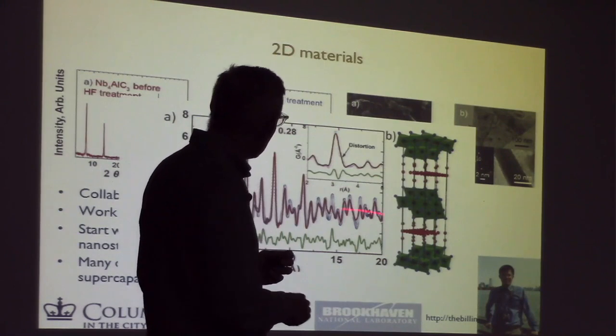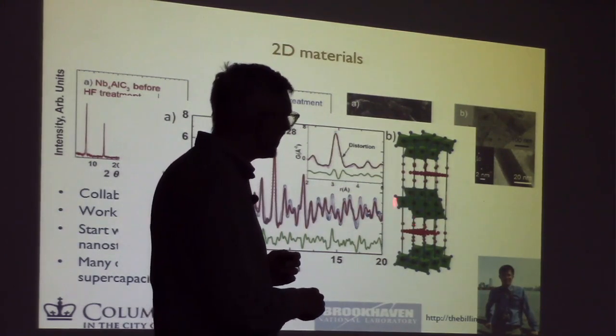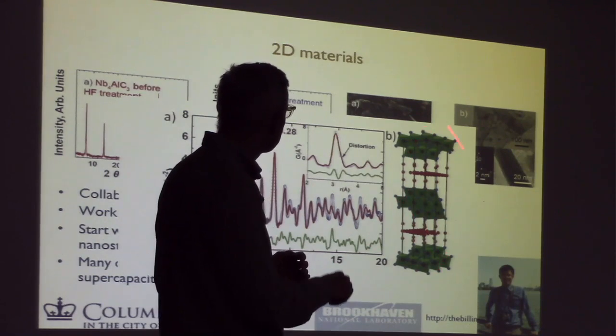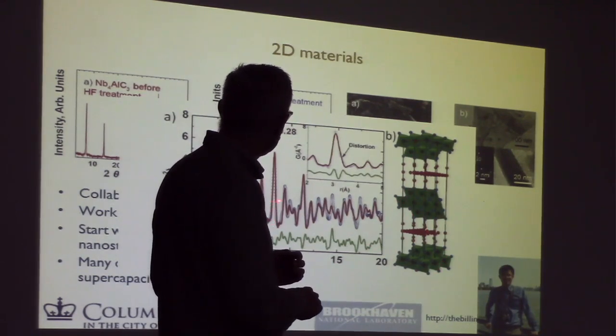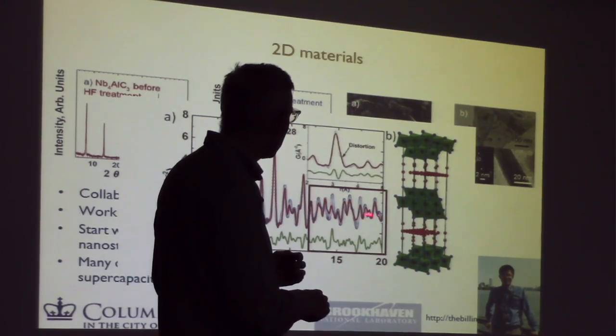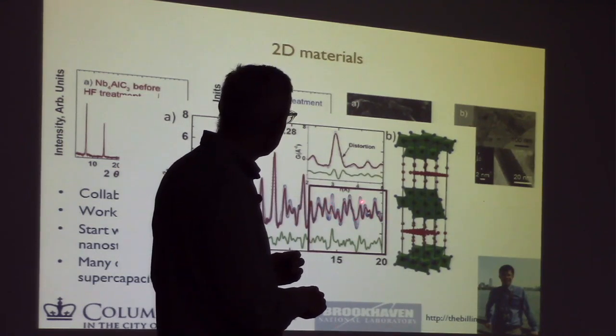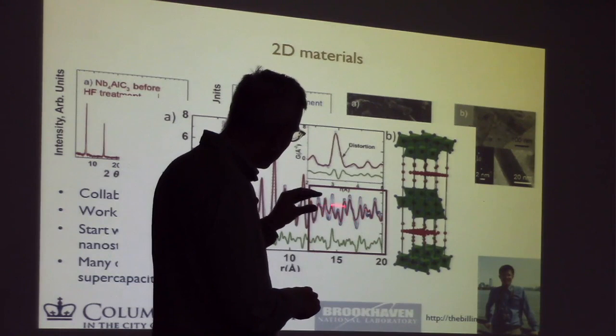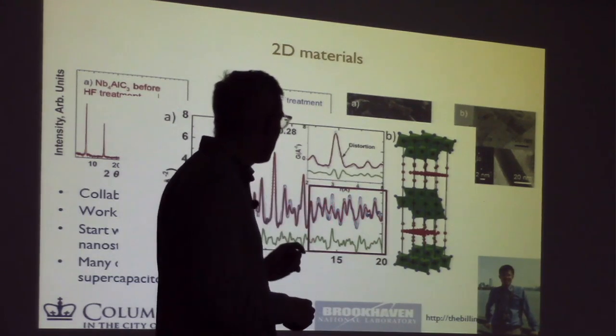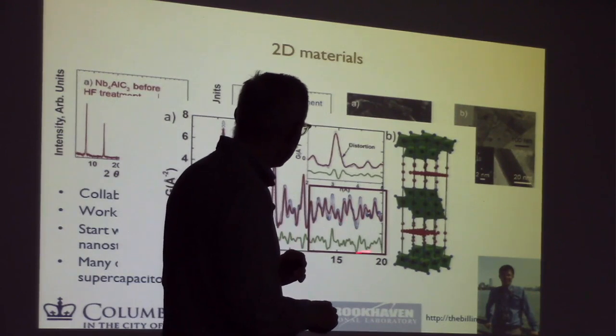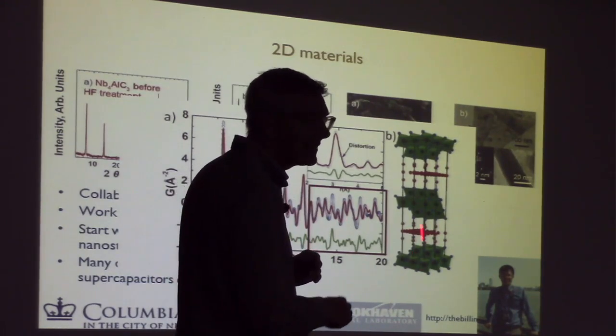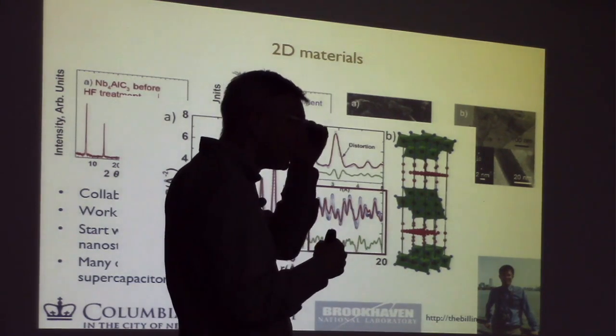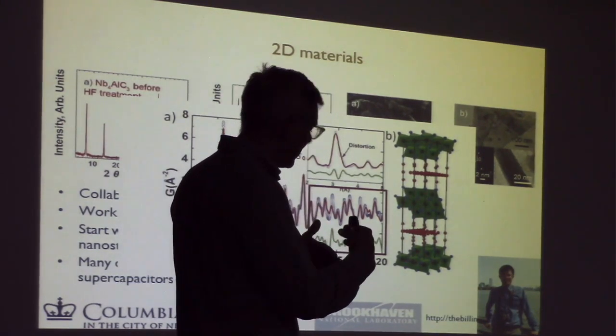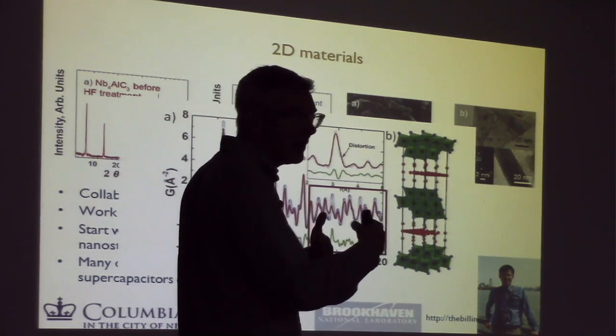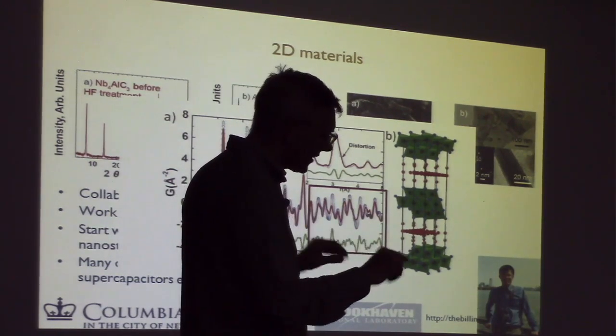So what we did is we did a model for one of these layers here. We did a crystal structure model which looks like this. And we find that we get actually quite good fits down here. But starting up here in this high r region, the fit gets bad. In fact, the data from the model is much more suppressed than the data from the material. And it turns out that this distance here is exactly the interlayer distance. And so again, this is the same problem that we had with the cadmium selenide, which is that the layers are becoming disordered, and we need a model where we just model individual layers.